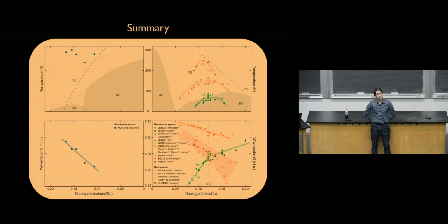But you could do it with current. So you can make a small device that has a small channel, perhaps a thin film, where you can inject the current, and then the current density would be very high because you have a very small cross-section in a thin film. And then with a nanometric beam, you can look into this channel where you have a large current density and perhaps see what happens now that you've suppressed superconductivity with large currents. That's one idea that we have.